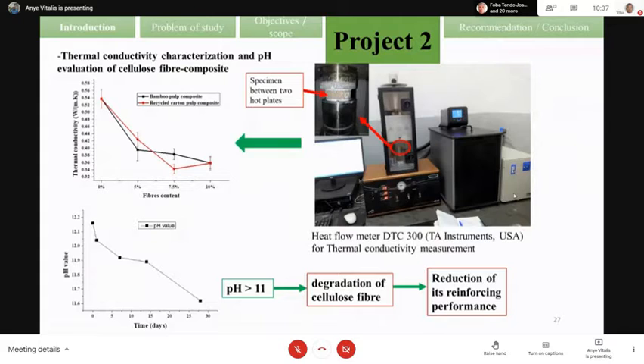So also we study the thermal conductivity of our base material. We realize that the more we introduce the fiber, the more our thermal conductivity is reduced, due to the fact that the fiber with a low density helps to reduce the thermal conductivity of our material. Also, we study the pH evaluation because the cellulose fiber can degrade in a high pH medium. So we realize that from 1 day to 24 days, there is a reduction of the pH, but after 28 days, the pH is still higher than 11, which shows that the fiber can be degraded with time in the alkaline-based matrix.